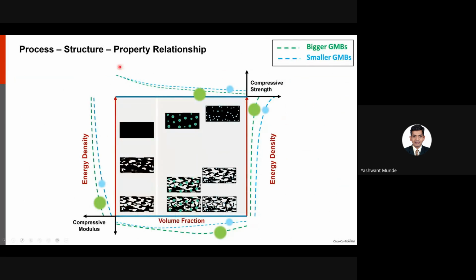Here's a process structure property relationship map we developed, where we show that as we increase the energy density, that is the energy supplied during the printing process, we go from a segregated matrix to a solid matrix at some point, as expected. But as long as we're in the segregated zone, the larger particles have higher compressive modulus compared to the smaller particles. Also, there is a limiting volume fraction beyond which the compressive modulus decreases for both bigger and smaller particles, and that volume fraction limit moves to the left, or is reduced, when we have smaller particles.